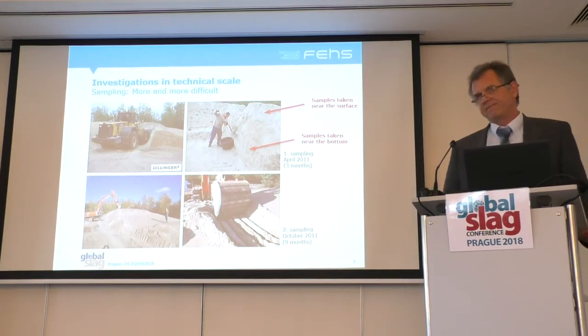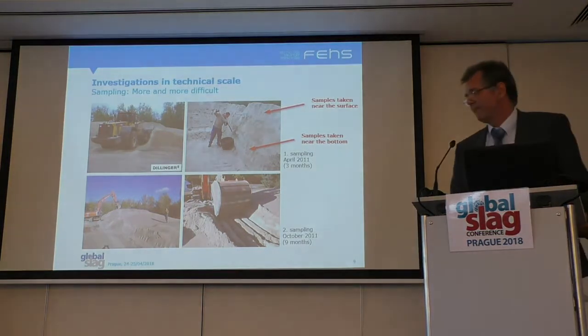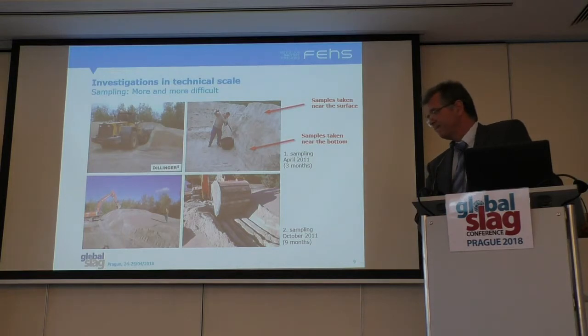Just to finalise the discussion, I wonder what the total change per particle of granulated blast furnace slag is that has reacted over the time. If you imagine, equate it with the planet, if you like, the amount is equivalent to the atmosphere. It's a tiny, tiny thickness on the surface of the particle, which is less than a 10th or 100th of a percent of the overall particle size.